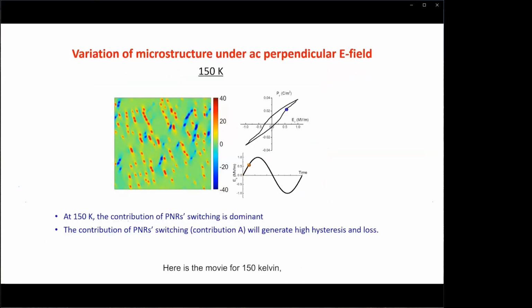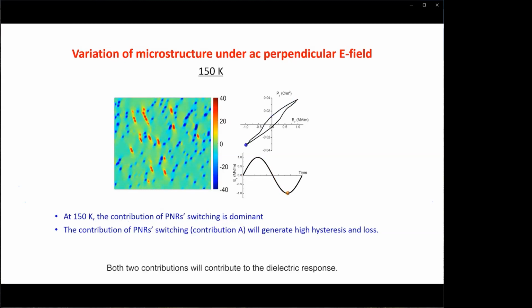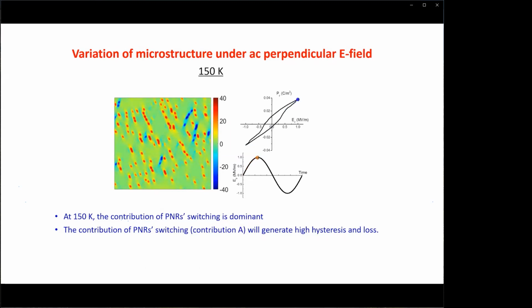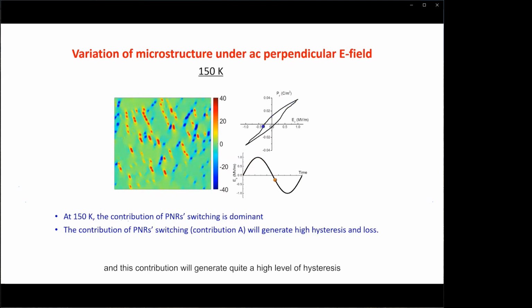Here is a movie for 150 Kelvin, by which we can clearly see the contribution from polar nanoregions. Both contributions will contribute to the dielectric response, while the contribution of polar nanoregion switching is dominant. And this contribution will generate quite a high level of hysteresis in the PE loop, as you can see here.